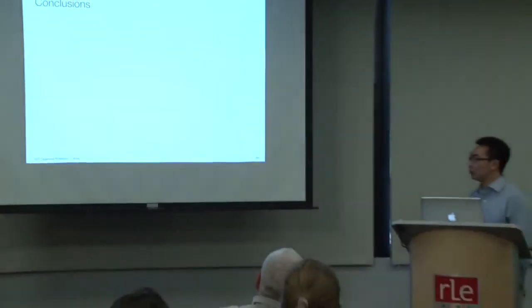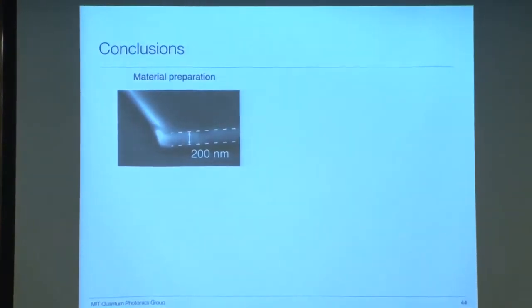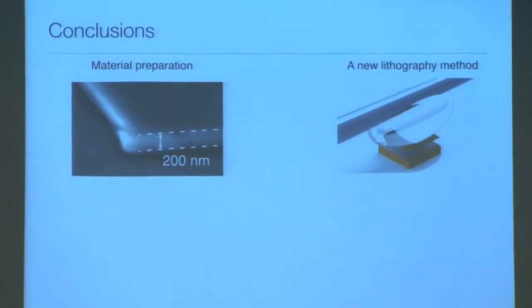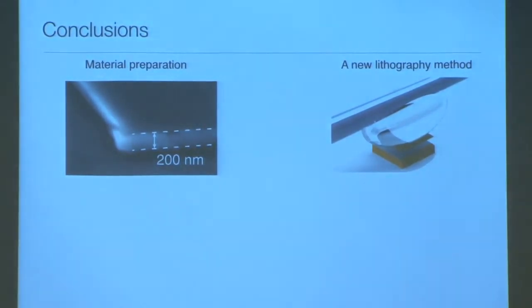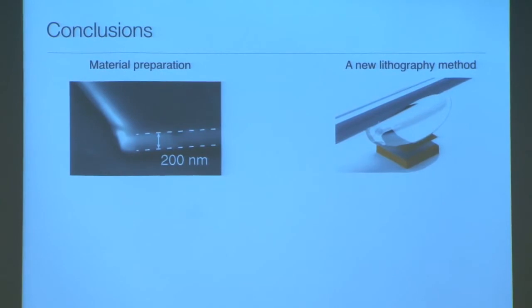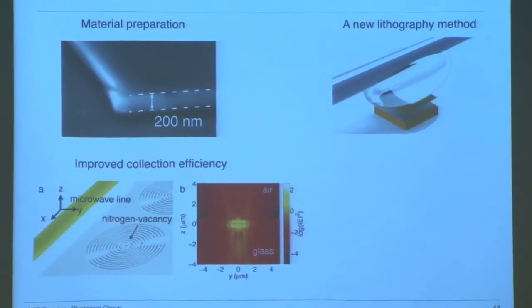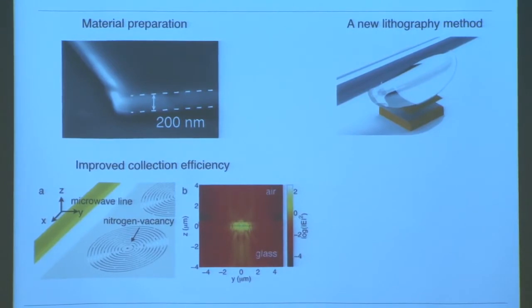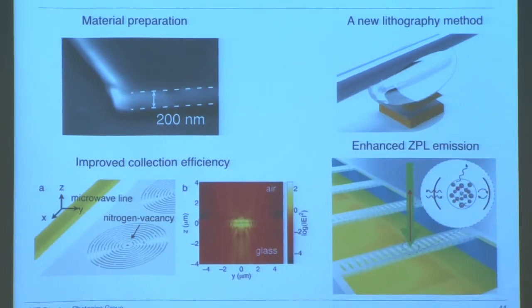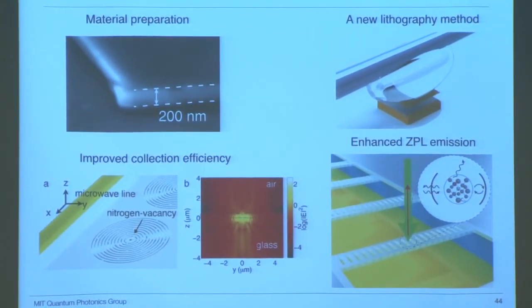Then I will conclude my talk. My goal of the PhD is to achieve an efficient spin-photon interface. For that, I first did material preparation, that is, fabrication of 200 nanometer diamond membranes. Then I developed a new lithography method that can etch nanostructures into these diamond membranes. The resultant device 1, the bullseye grating, increased the overall collection efficiency, and the photonic crystal cavities enhanced the NV ZPL a lot.